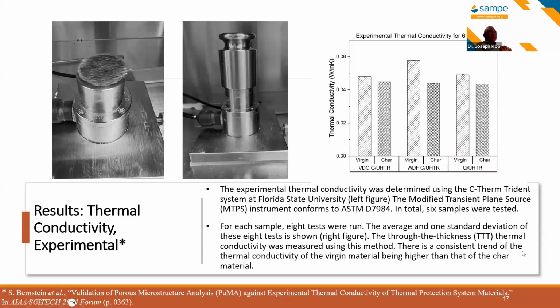Okay, this is something that we are working with Florida State on, where they were able to measure the thermal conductivity using their C-Therm system, and we were able to measure the virgin and the char of some materials that we're developing. This is a graphite UHTR. This is another graphite UHTR. The third one is a quartz UHTR. We were able to measure these.